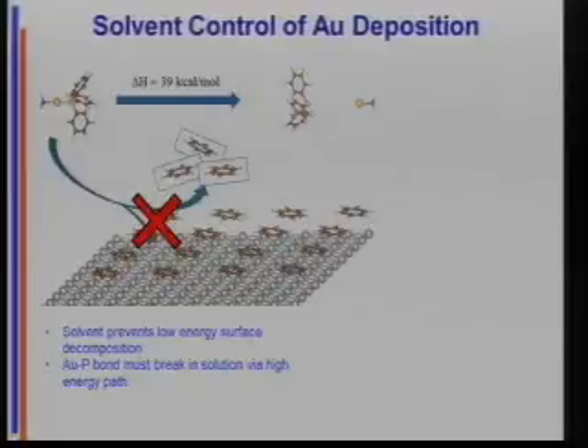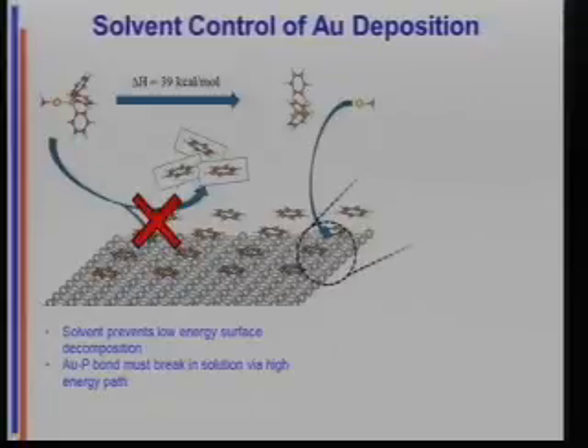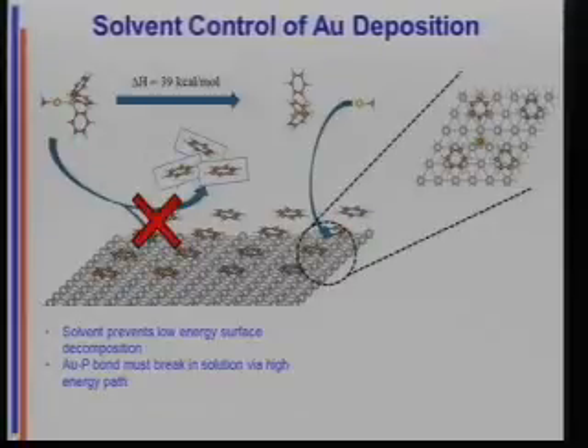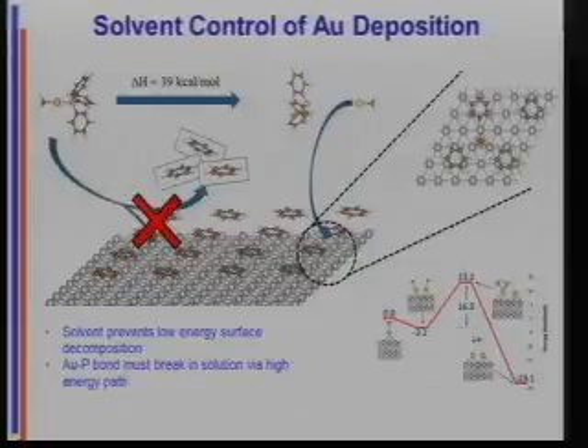This is a reaction that Jay Kochi studied very well in the 1980s. And now we have methyl gold fragments, and we adsorb those onto there. Okay, so they're tucked in between. And here's a reaction surface for one of them. Here they are migrating together to make a dimer. Then you see migration of the methyl from one gold to another.